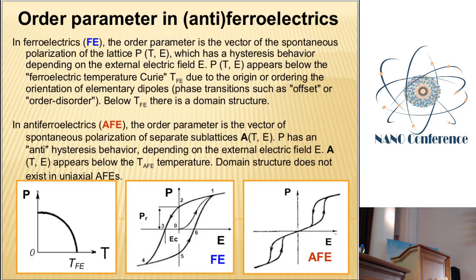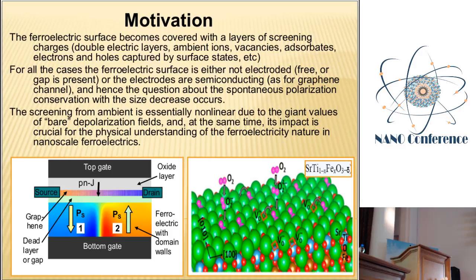Well, another effect different from the size-induced phase transition is the surface influence on the polarization. When you have an electrically open surface, in the sense that you have some layer, for instance, an oxide dielectric layer in the system which contains a ferroelectric film, then a graphene channel, and then a top gate, this dielectric layer also prevents conservation of the ferroelectric state. Why does this happen? This happens because the bound charge that creates the ferroelectric polarization tries to scatter in the gap, and the electric field which is formed in the gap decreases this polarization.